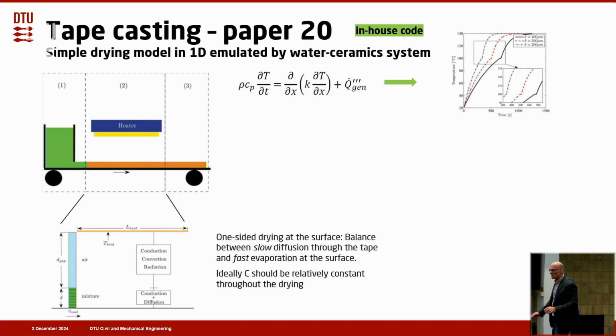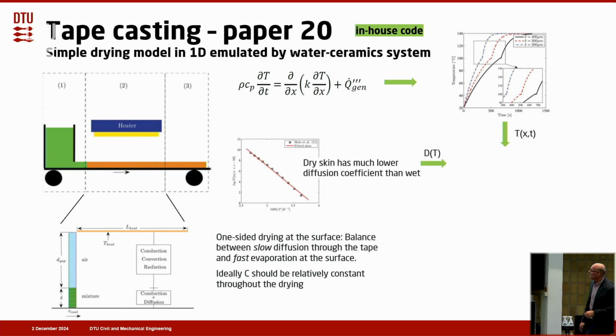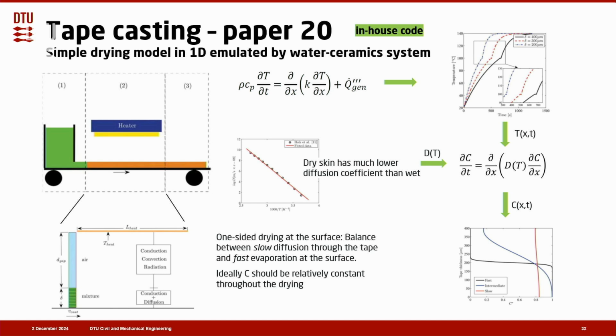So we made a simple model for the heat conduction equation in 1D. This is what you see here, very simple. Then we got some temperatures. And then we also realized that the diffusion coefficient for the dry skin has a much lower diffusion coefficient than the wet material. Combining that, we could solve Fick's second law, and then we could get the concentration profiles through the tape for fast, intermediate, and slow drying.